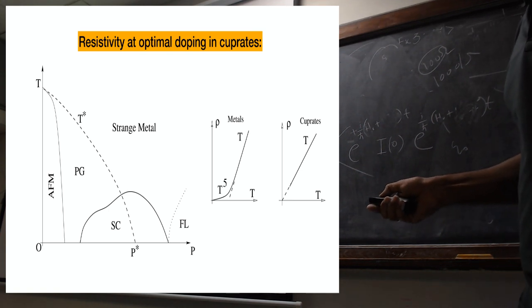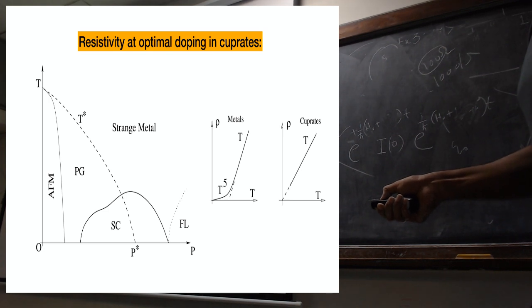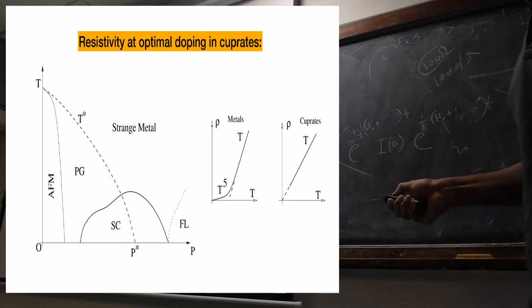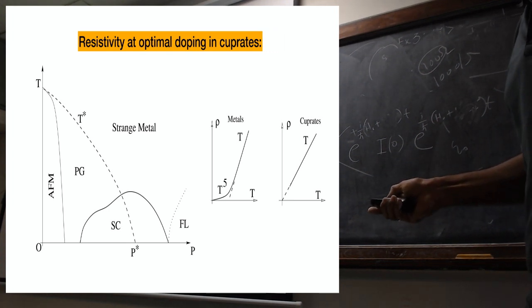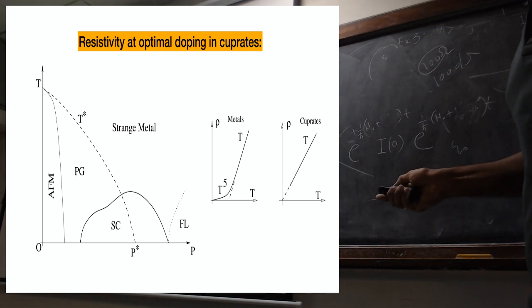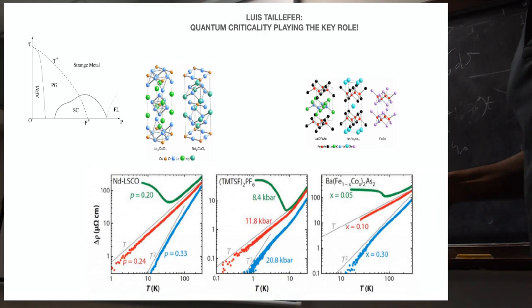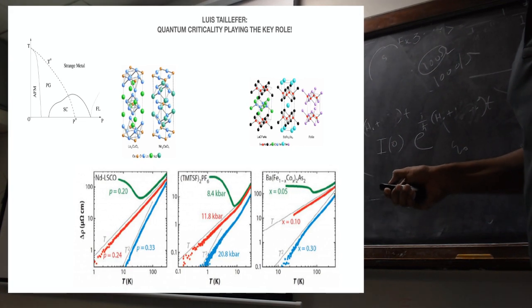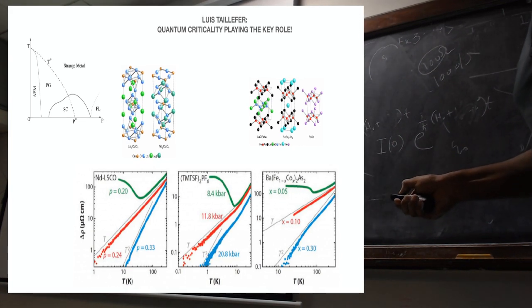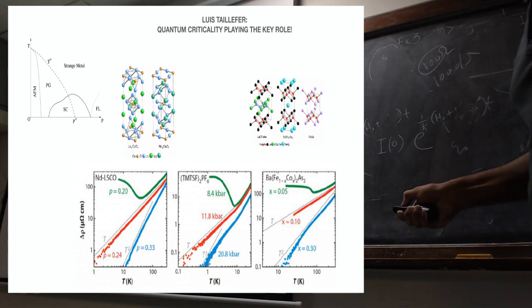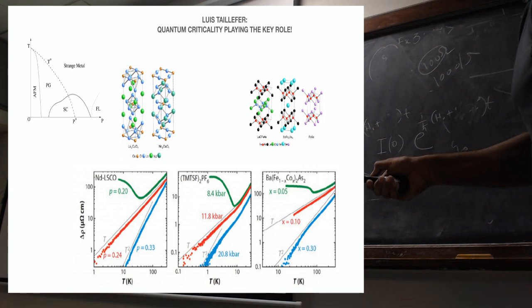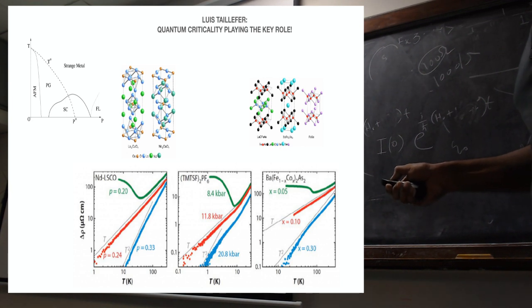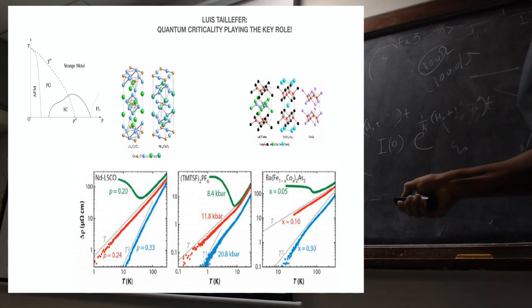Without any pressure. This is the quantum critical point. Here no pressure. 800 Kelvin is like 600 degrees centigrade, something like that, very hot. Yeah, so something really novel is happening. But this T linear is not only seen in cuprates, it is seen in iron-based superconductors. This is an example of an iron-based superconductor. At a doping of 0.1, a similar phase diagram is true for iron-based superconductors also. It is T linear there, and the rest becomes different from T linear.